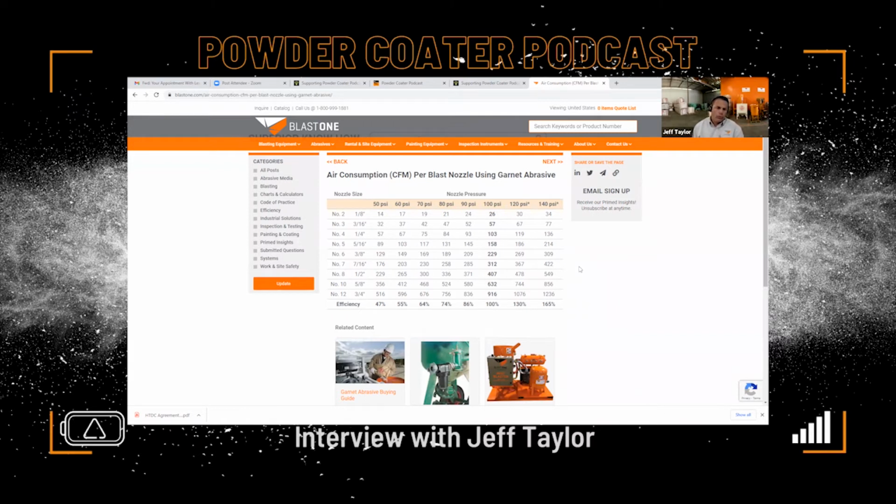For every 1 PSI you lose under 100, you lose 1.5% production. So the difference between 80 PSI at the nozzle and 100 PSI at the nozzle is actually 30% production. So just by simply going to a smaller size tip and getting a higher nozzle pressure, you may actually increase your production, because although you might have a smaller nozzle pattern, you have a significantly higher cutting speed. And the higher your cutting speed, the lower your abrasive consumption.